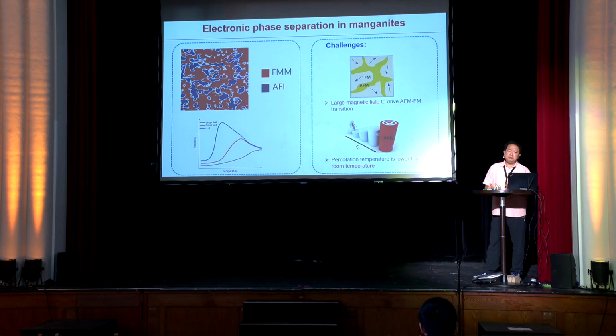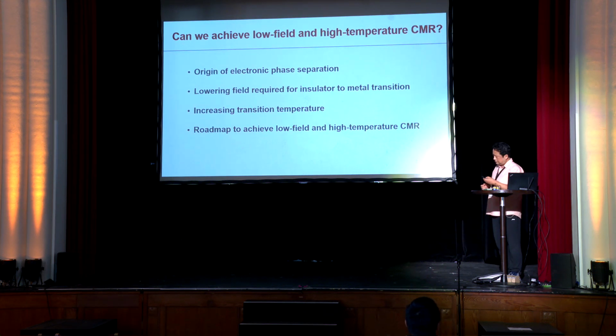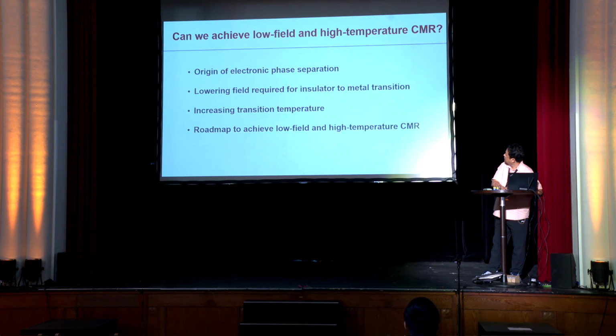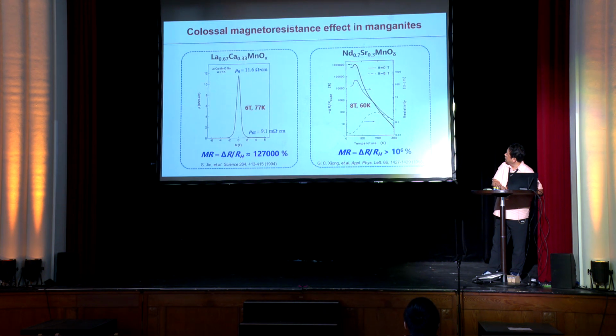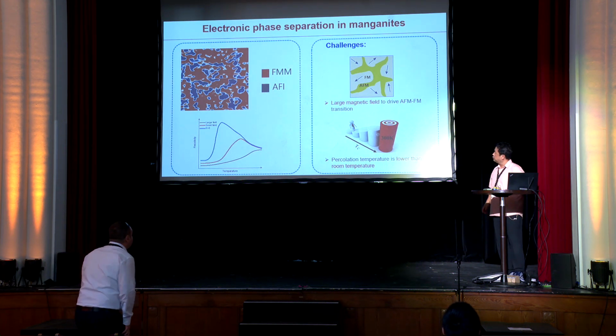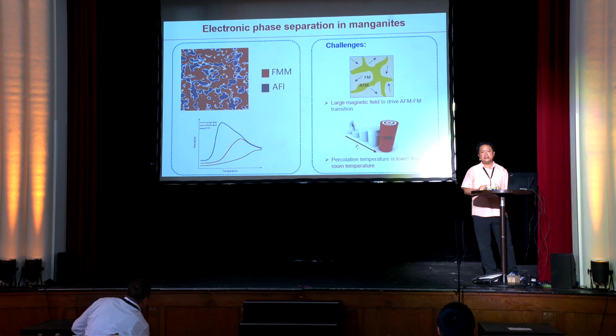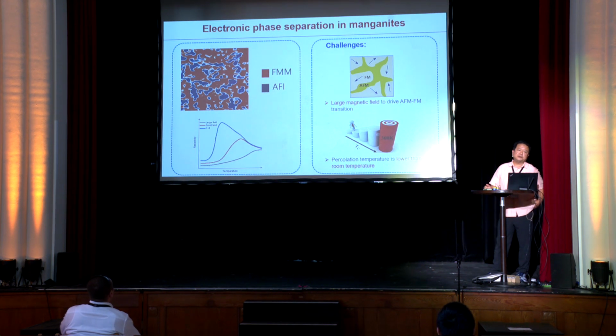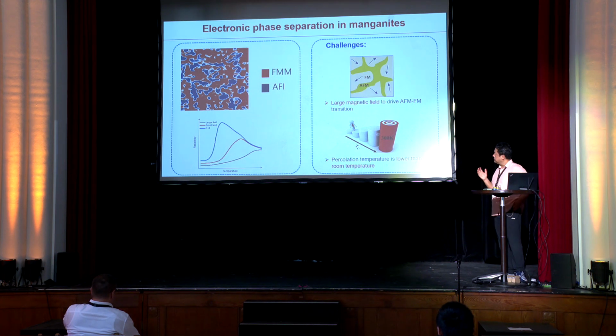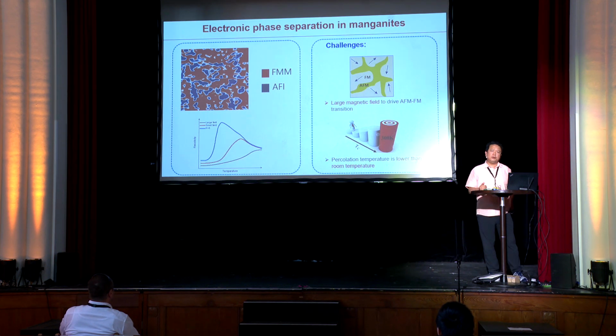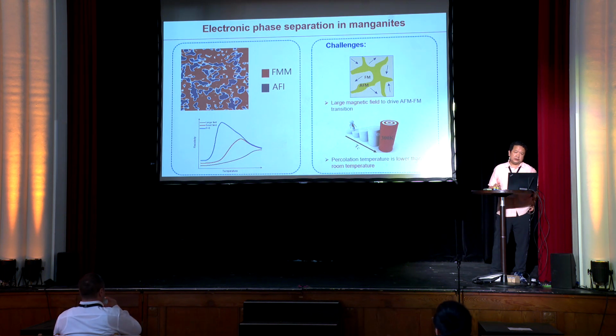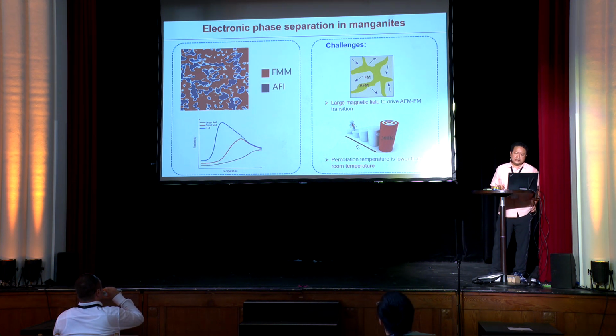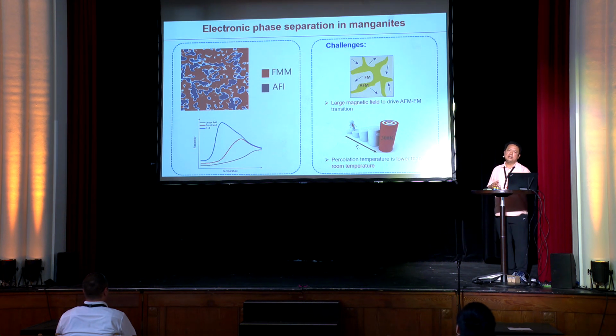However, the problems for application are two. The first is that you really need a very large magnetic field to drive the antiferromagnetic to ferromagnetic phase transition, on the order of Tesla. That's too large for any applications. The second is that the transition temperature is usually well below room temperature, which is also not very useful for general application purposes. These are the two problems that people have been working on, but with very limited success.